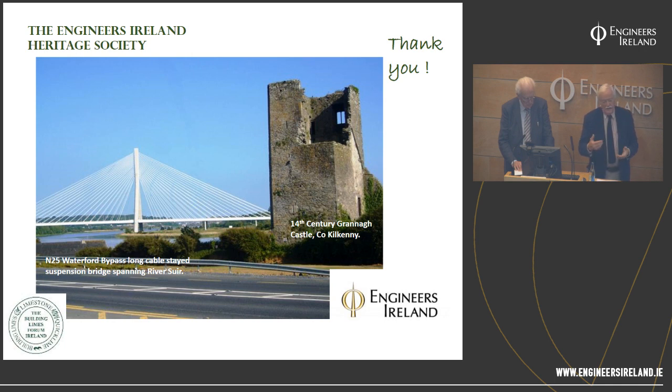Even an engineer designing a mortar, not that they bother for an ordinary foundation if it's brick, won't be looking for a concrete. He won't be looking for more than 2 or 3 Newton anyway. That will be by design, by the spread and so on of it. If you use too strong, parallel to compressive strength is brittleness and inflexibility. So if you go to too high a compressive strength, you get too strong a mortar. And that's why cement is unattractive and not used, and fails, for pointing for masonry work most times. Is that the question? Mm-hmm.